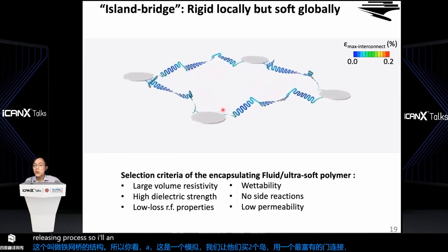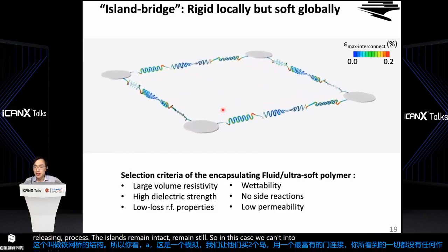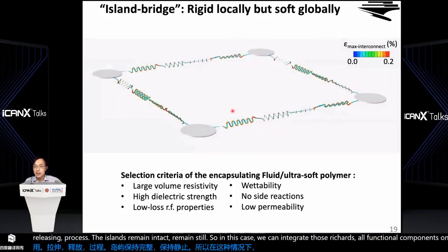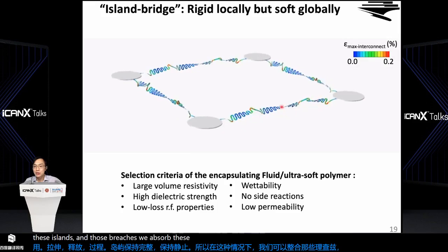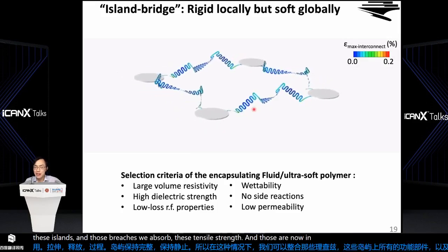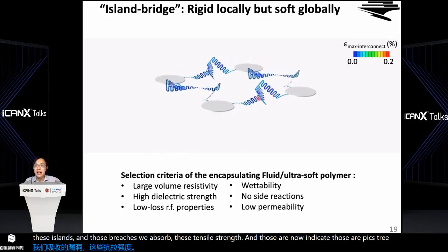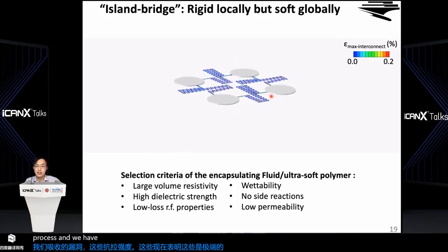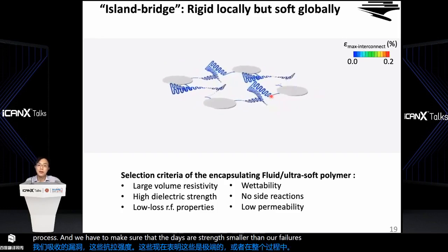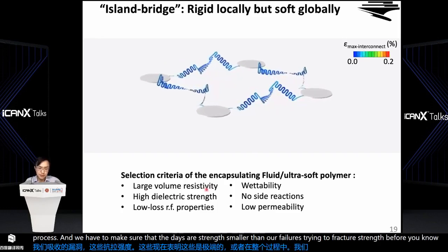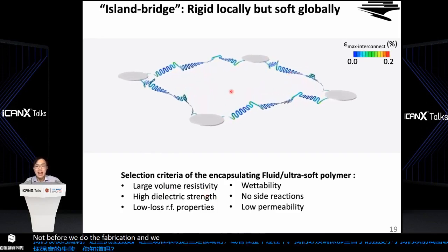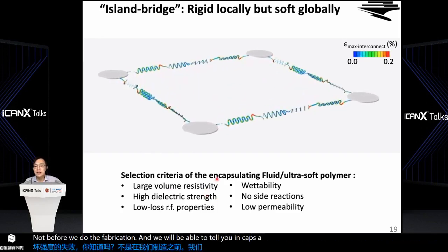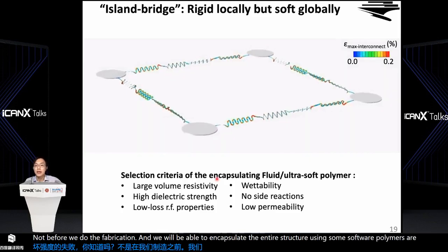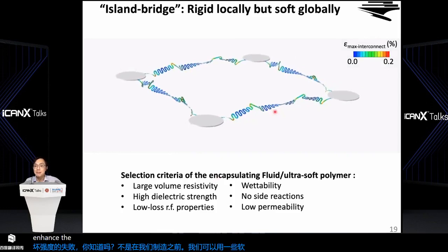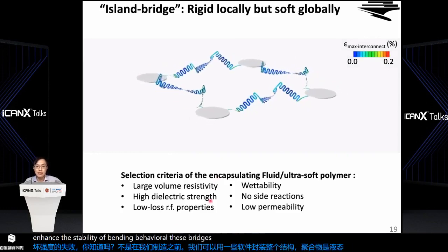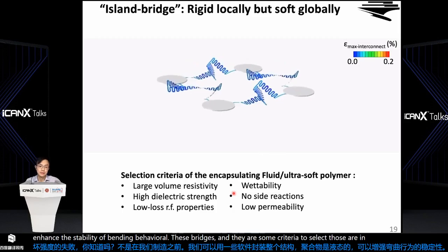So in this case, we can integrate those rigid functional components on these islands, and those bridges will absorb this tensile strain. And those non-uniform colors indicate those peak strains in this entire process. And we have to make sure that this strain is smaller than the failure strain, the fracture strain, before we do the fabrication. And we will be able to encapsulate this entire structure using some soft polymers or liquid to enhance the stability, the bending behavior of these bridges. And there are some criteria to select those encapsulation materials.